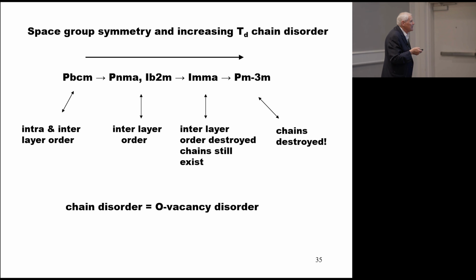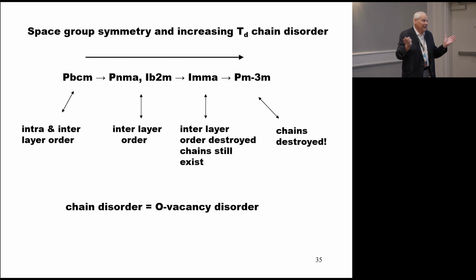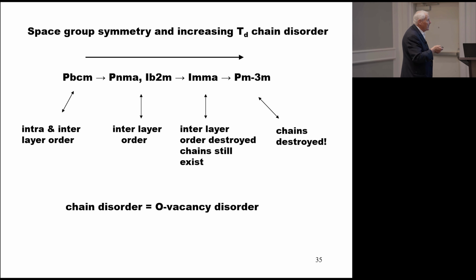Now, the interesting thing is that the space group actually tells you right away how disordered or ordered the chains are. For example, in this case, Pbcm, we have strong intra and interlayer chain ordering. In Pnma and Ib2m, we have interlayer ordering only. In Imma, the interlayer ordering is completely destroyed, but the chains still exist. They're just randomly distributed. There's no right-handed, left-handed correlations. And then finally, of course, we can go all the way back to Pm3m, where there are no more chains. Everything is completely destroyed. And so the space group symmetry is diagnostic of basically the oxygen vacancy disorder.